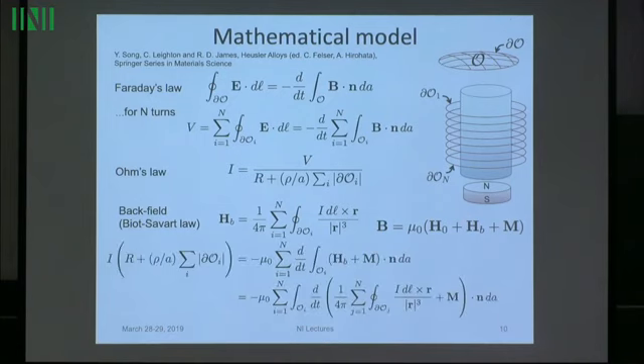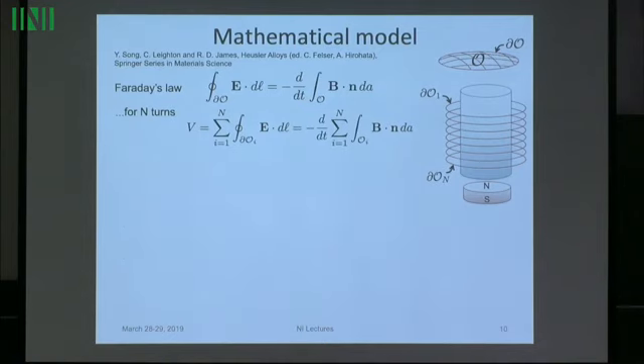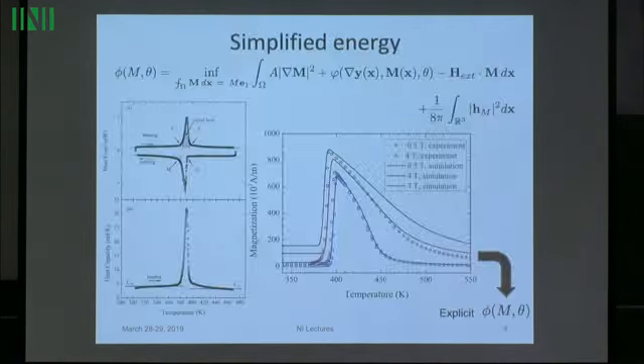So you get, with these kind of simplifications, of course, the main complication then is how do you get this magnetization in the specimen itself. The magnetization in the specimen itself comes from the previous slide, so it comes from minimizing this energy. So we're going to minimize this energy to get the magnetization, apply a temperature which depends on time, and solve this equation. So this is a very simple model.